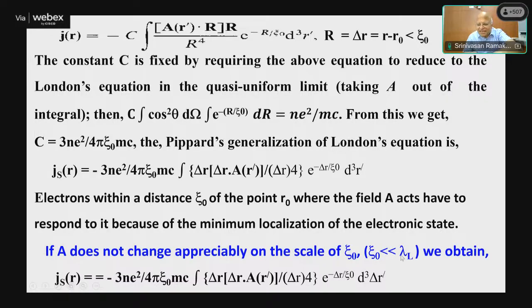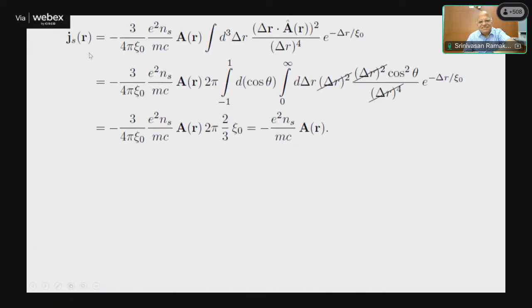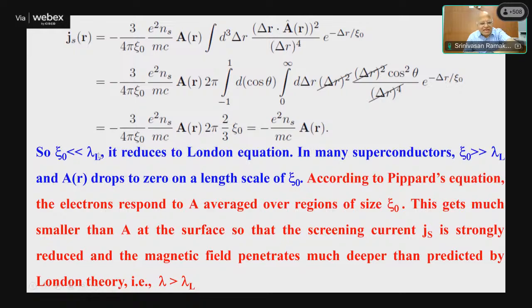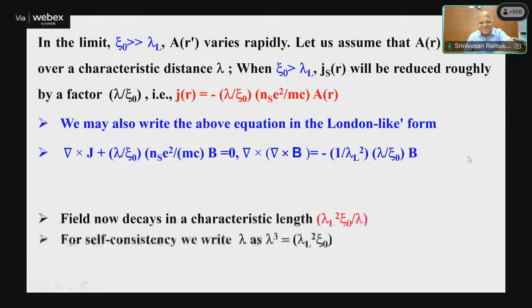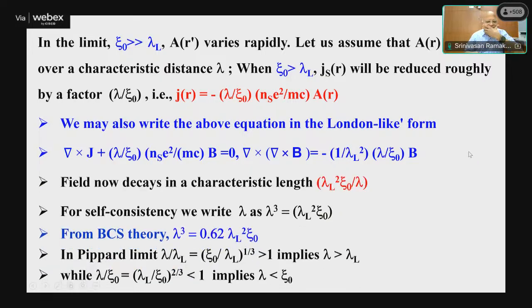So what happens is that in cases where the London penetration depth is much larger than the coherence length, it will reduce to the London equation. J is proportional to the vector potential A of r. But in many superconductors, at least in type 1 metals, the coherence length is larger than lambda. So London's work will not agree with the experiments. So now the new penetration depth for Pippard will be given by this expression: lambda cubed is lambda squared times xi naught.